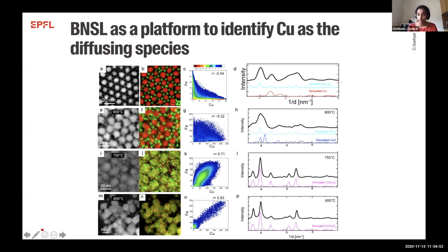We relied heavily on elemental maps of these crystals, as well as electron diffraction patterns, to understand the transformation of these materials that is taking place. In addition to the elemental maps, we also used a colocalization analysis of these maps so that we can quantitatively measure the homogeneity of the sample. In these colocalization maps, if we have the density over the axes, it means that the copper and the iron are actually separated, as in the case here. The closer the two densities move towards the diagonal, the more homogeneous the crystals are. In addition, we also used a correlation coefficient as a quantitative number to have an idea of the homogeneity of the crystals.